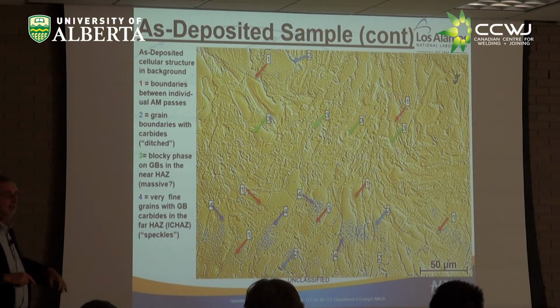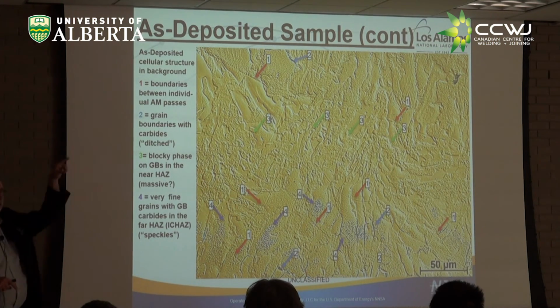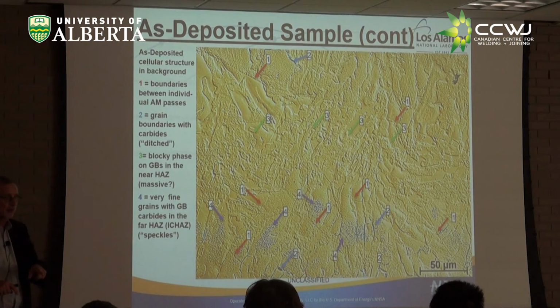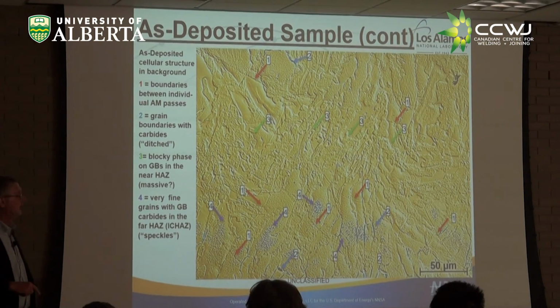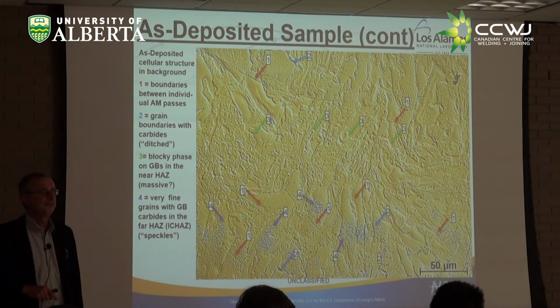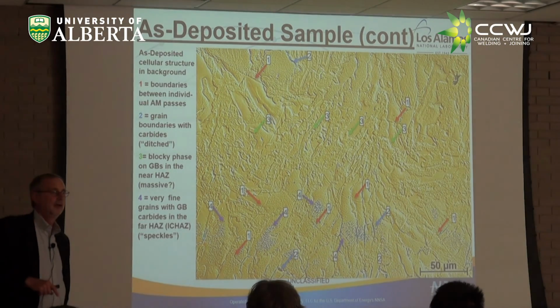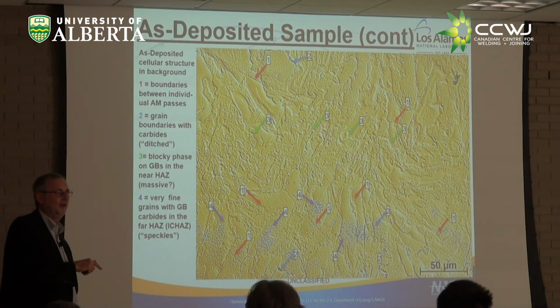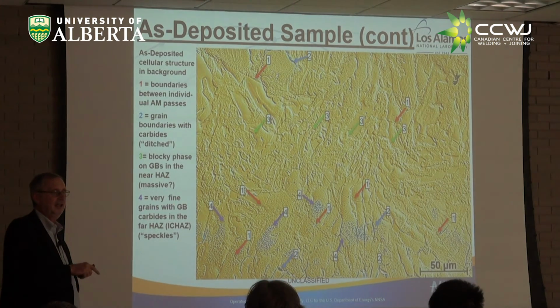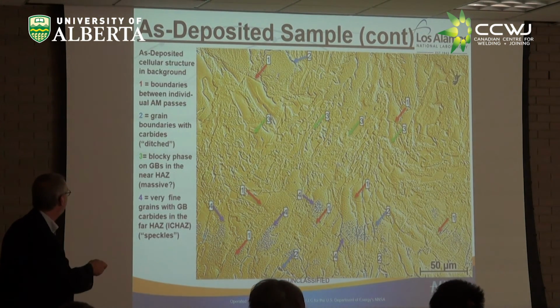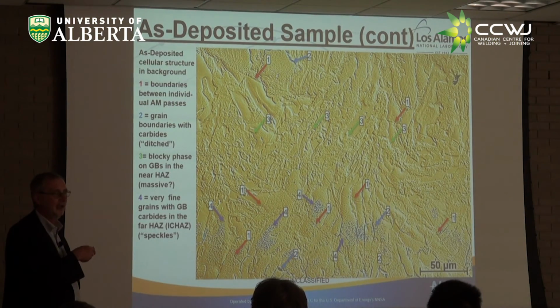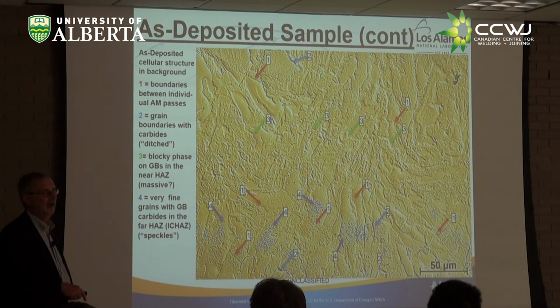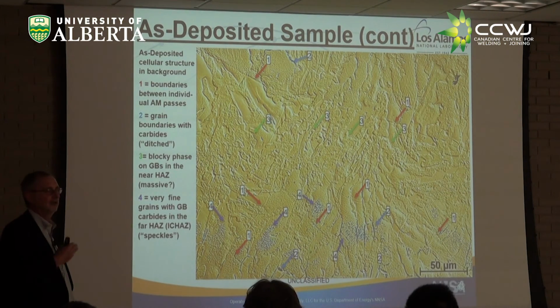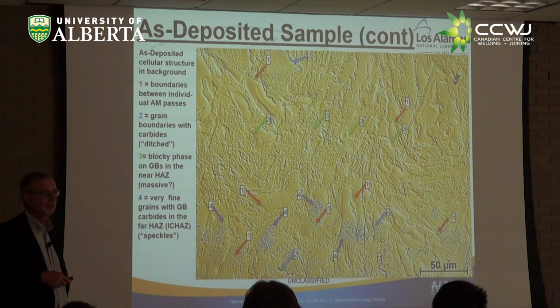So when you say it's retained, it occurred during reheating and cooling, and that's why it's retained? Okay. Like delta ferrite at high temperature, but that's not going to transform into austenite. I think it's all delta ferrite at one time that is now retained. Even the solidification microstructure was delta ferrite, is now alpha ferrite, and then it becomes sort of a semantic argument over whether it's delta or it remained from high temperature. Yes.